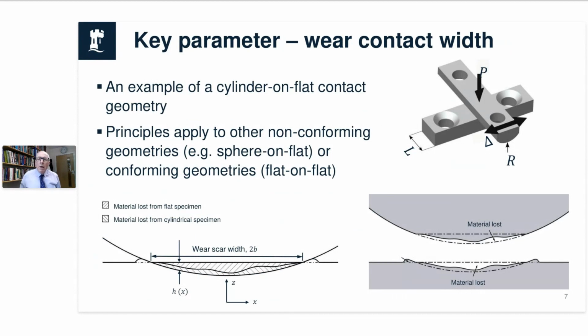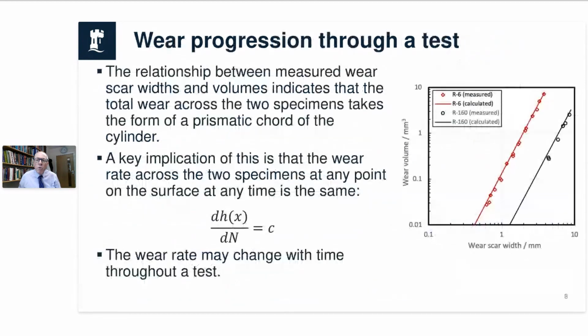So as we've got it here, the image that I've got at the top is the way that we do our tests. We have a cylinder on a flat, and we move the cylinder perpendicular to the axis of the cylinder. We get a wear scar width, but that wear scar increases in size through the test. We know that the wear scar always takes the form of, essentially what you might say is the segment of the circle, the prismatic segment of the circle, is what we've shown through tests like this. So I'm not going to really spend very long on that. You can go and have a look at that in some of our work that I've referenced.